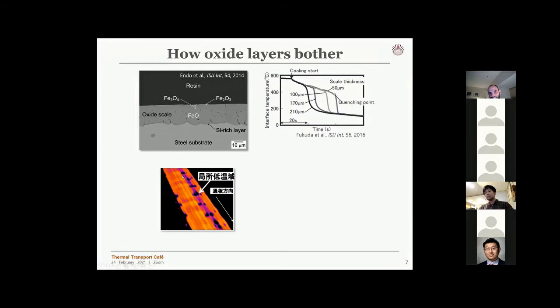So you have this local oxidation on the hot rolled material - this is a thermographic image of the process, showing local cold regions. If you have oxide layers at random areas, you get faster cooling on those particular regions, and the rest has rather lower cooling performance.